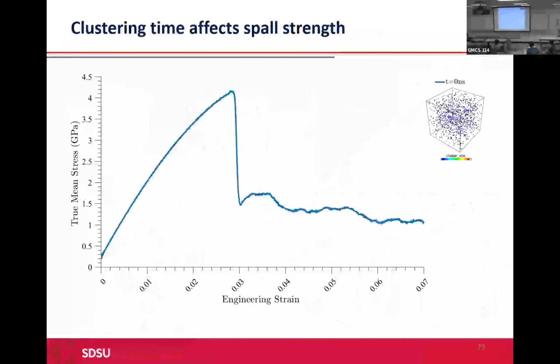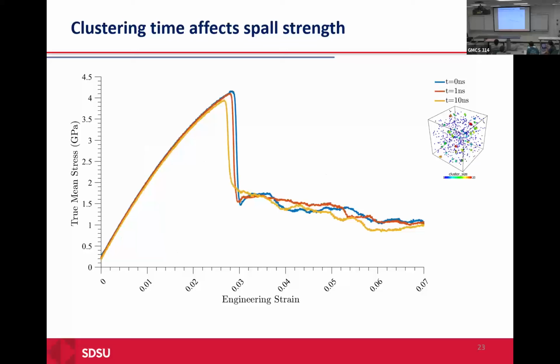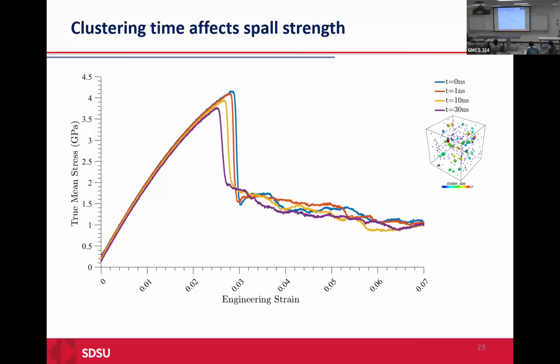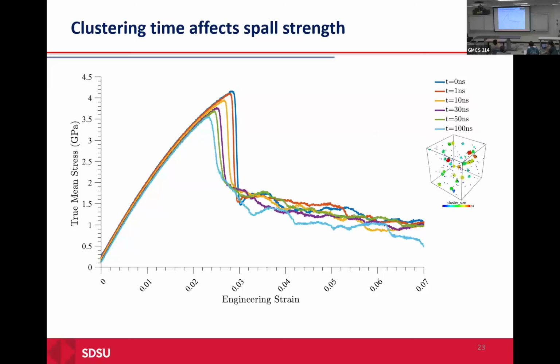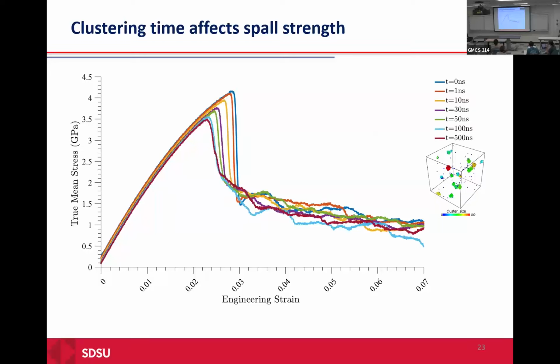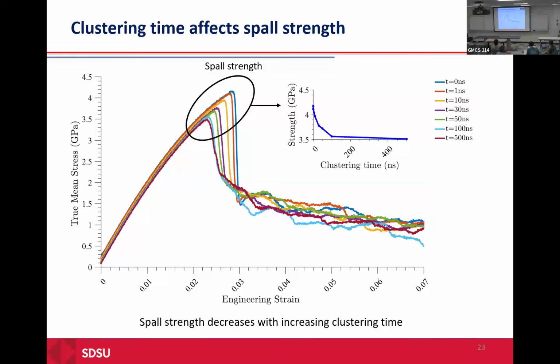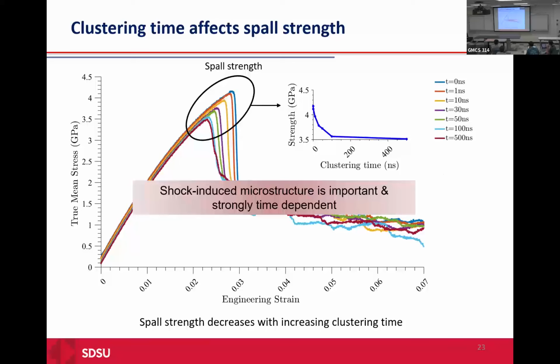We did this modeling simulation for different time steps. At each time step, we got the microstructure and applied load, hydrostatic load, and got the stress strain curve from the simulation. We ran it from 0 nanoseconds to 100 to 500 nanoseconds. And then we got the spall strength, or the maximum stress of the material, extracted from those data. Then you can see that the strength is decreasing as we increase the clustering time.